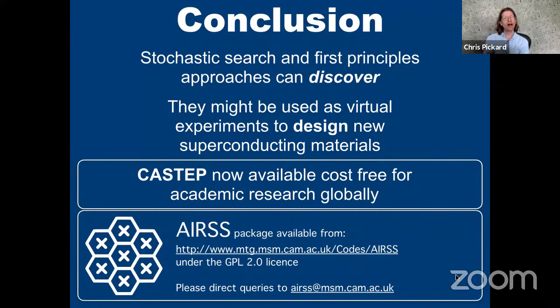Okay. So absolutely, I would say that's where the frontier is now. I gave a talk and a similar question was asked: could you predict quasicrystals? These obviously are not periodic in the 230 space groups. The answer is, quite hard at the moment, but the aluminium phase that we found at terapascals was actually a host-guest phase that was incommensurate. Although I used the computational methods to find approximants, when we published the result, we actually fitted a parabola and said the incommensurate ratio is some irrational number, so not a periodic structure. So our prediction does go beyond those space groups.